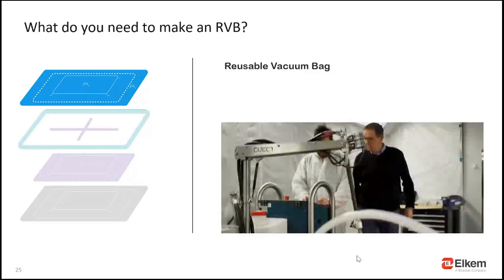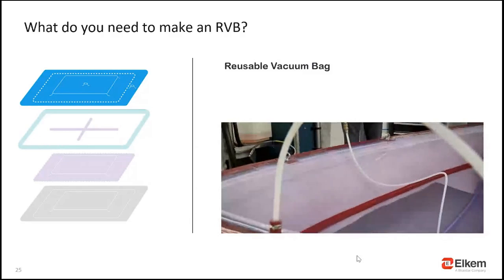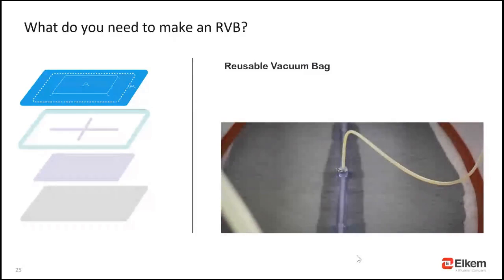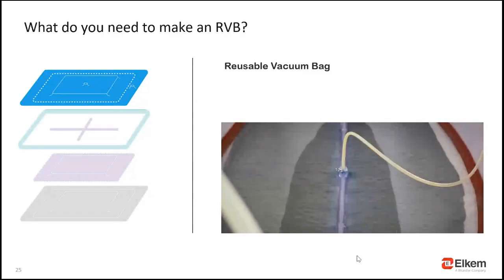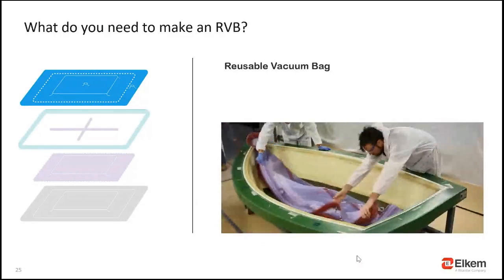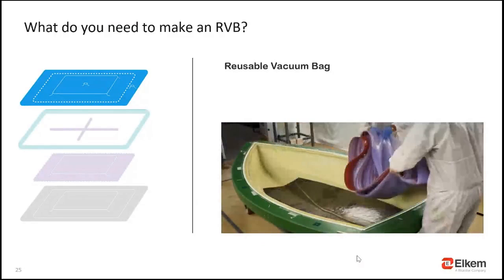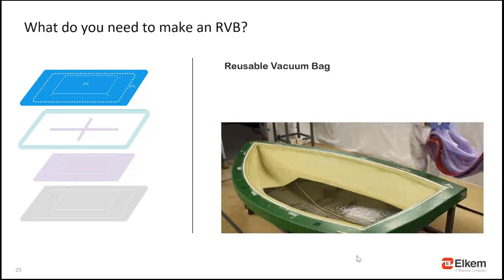With a perfectly fitted RVB, the infusion process is going to be as fast as in the classical infusion. The vacuum forces the resin to flow inside the fiberglass mesh, avoids air bubble formation, and fulfills the whole piece. After resin curing, the RVB can be demolded as the silicone has a natural property of easy release.